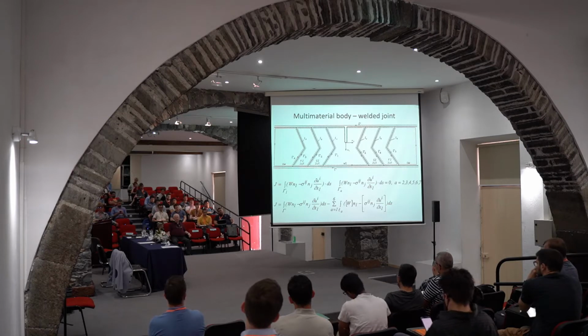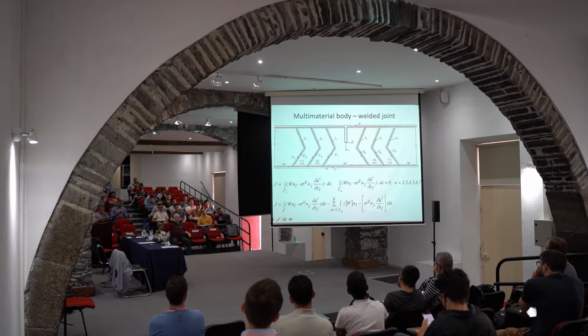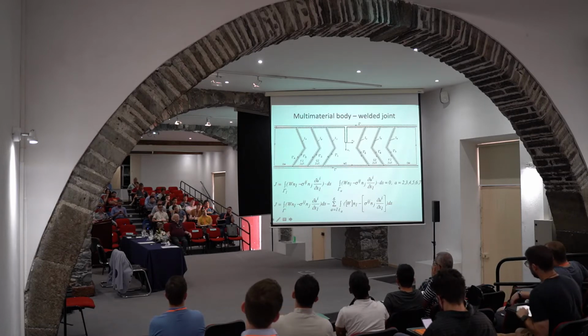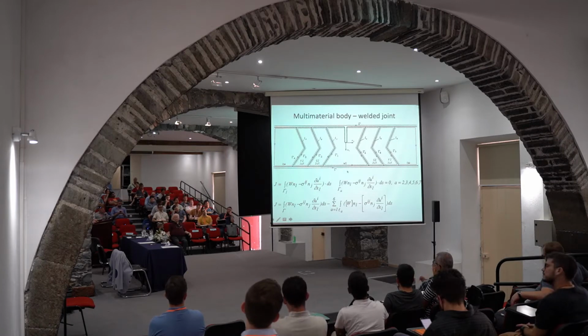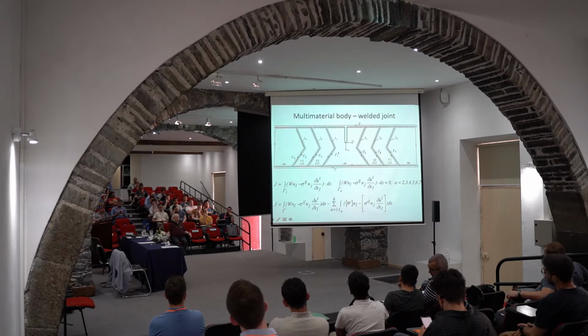But let's see. First of all, if we have just the integral of part gamma 1, which is this one, which is inside weld metal, then it is path independent, and that value should be okay. But as I just said, in practical terms, what we can measure and what is measured in the direct integral technique are strains along outer surfaces, because we can't get into the depth, and these strains will enable us to evaluate the integral, but that part is not path independent. Gamma 1 is, gamma is not.